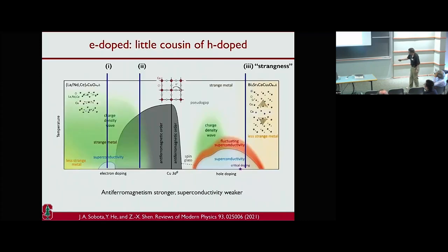So what these results suggest is that we used to think the electron doped system had a wide range of doping and temperature that seemed to be a boring, long range order and all that. But what is emerging now is that there seems to be an intruding charge density wave. Then there might be a pairing in this one. Maybe the pairing is higher than we think. As a corollary, those physics need to be separated from the long-range Mott state at half filling. Certainly at 4% doping, there are a lot of low energy excitations already built up. So this phase diagram might be richer than we think. That's what I would say the surprise is.